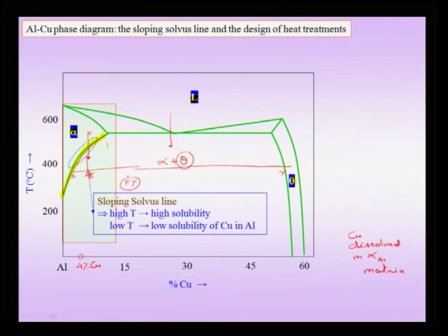That means that if I slowly cool I will produce a theta precipitate, and normally when slowly cooled the morphology is such that the theta precipitate is very large. That means that I would have theta in my matrix, and the overall size of these theta precipitates will be very large, because I would have a few nuclei which grow very large, and therefore, I would have a coarse precipitate morphology of theta phase in the matrix. Now, such a material is not very good for hindrance of dislocation motion.